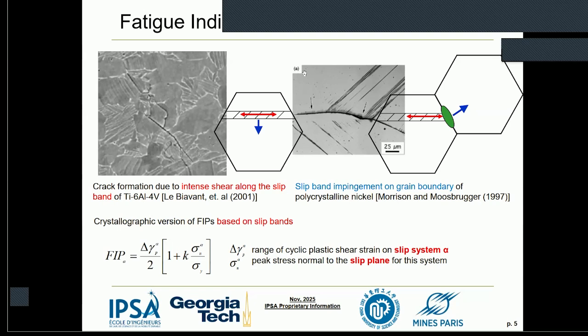So this FIP is a function of delta gamma alpha, in other words, the plastic shear strain on each slip system, as well as its corresponding normal stress. This indicates the plastic dissipated energy or power. So this is a typical way, and in fact, there are many different formulas for the FIPs.